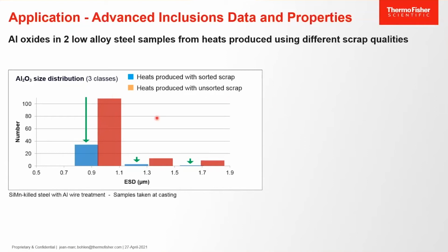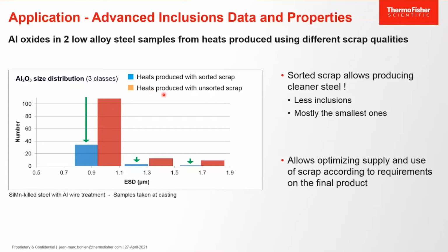As you can see on the graph, there are more inclusions monitored with the heat produced with unsorted scrap. And there are also more of the biggest inclusions. So clearly, a cleaner steel is obtained with better scrap. So considering this, you can make very interesting things. When purchasing scrap, you can really dedicate the best scrap for the best steel quality or grades and use the lowest quality of scrap for less demanding applications and customers. So this is also a way to adjust your cost.